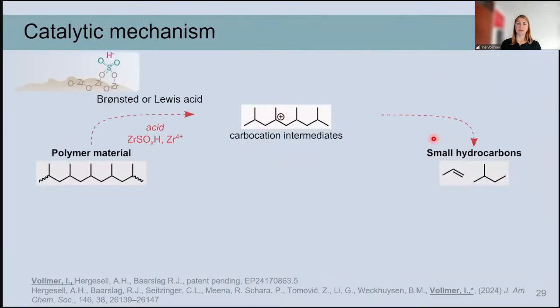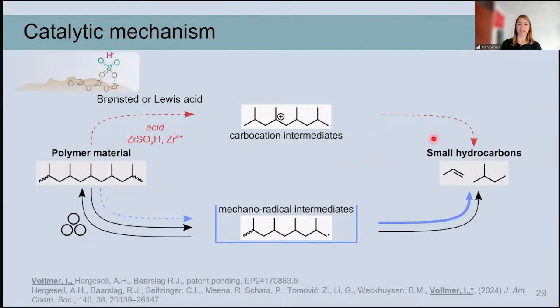So what we then speculated was that in mechanochemistry, we know that the carbon-carbon bonds actually break homolytically. So we would form radicals, as you can see here. And somehow we thought maybe our catalyst can interact with these radicals. It can either accelerate the initiation, or it can do something else. And so we tested whether we get more radicals when we add the catalytic grinding spheres, so whether the catalyst actually helps with the radical initiation.